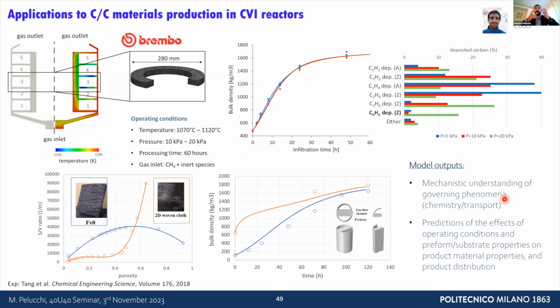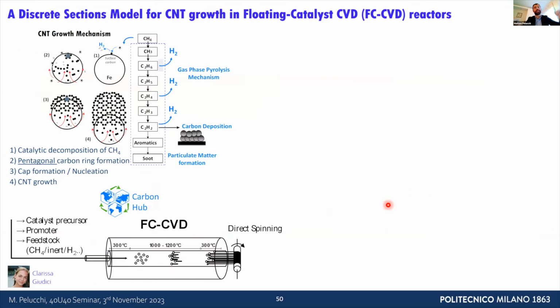If we know something about the preform used to densify these carbon materials, and we know the surface to volume ratio as a function of porosity, we can also predict their impact on bulk density in infiltration processes. Final step is extending this to a catalytic process, which we want to use in the context of Carbon Hub to produce nanotubes.